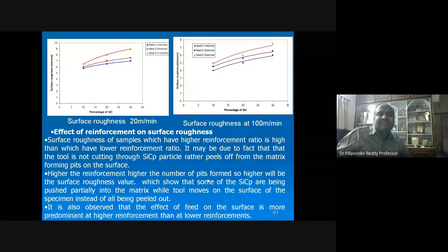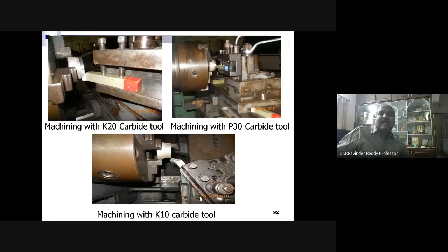from the matrix. The higher the reinforcement, the higher the number of pits formed, so the higher the surface roughness value. We show that some of the silicon carbide particles are being pushed partially into the matrix while the tool moves on the surface of the specimen, instead of all being peeled out. It is also observed that the effect of feed on the surface is more predominant at higher reinforcement. And these are machining with the K20 carbide tool.